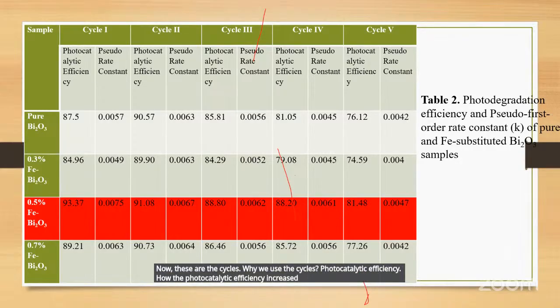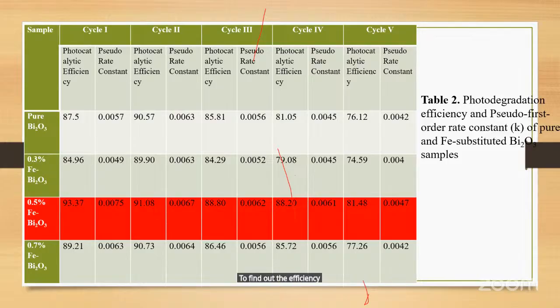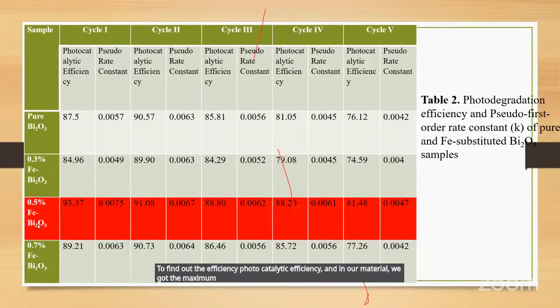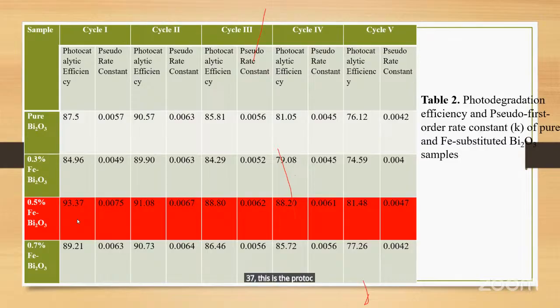Why we have to use the photocatalytic? Why we have to study the photocatalytic activity of the material? Because to find out the efficiency, photocatalytic efficiency, and in our material we got the maximum for 0.5% iron doped bismuth oxide, that is 93.37%. This is the photocatalytic efficiency. Which one is the highest in this?